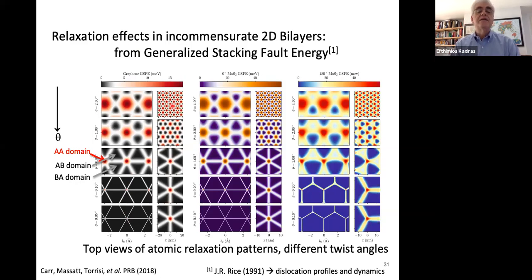So red is high energy, black is low energy. So you see that at 2 degrees, there's a mixture of high energy and low energy domains. And as you make the twist angle smaller and smaller, starting at about 1 degree, the regions clearly separate. So there are the high energy regions, red, which correspond to AA stacking, and low energy regions, which correspond to AB or BA stacking domains. And these are the black regions, and the white lines are the domain walls between them. From this range of values of twist angle and below, nothing changes in the pattern. The only thing that changes is that the black regions, the low energy regions, expand and become larger.